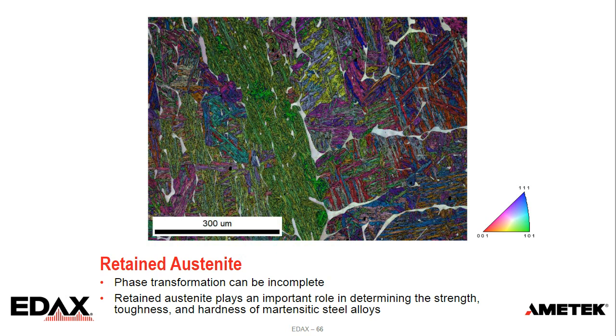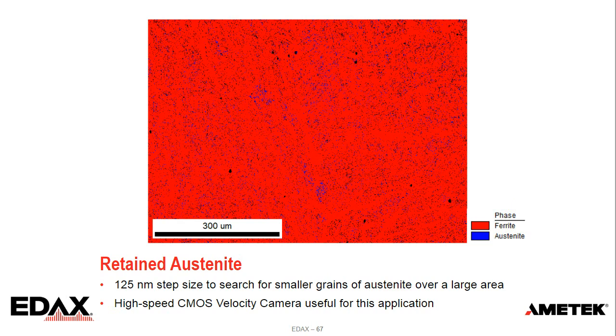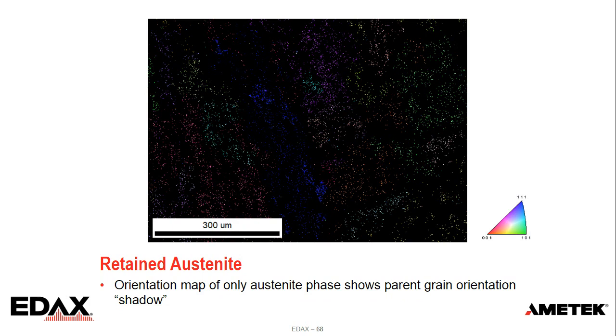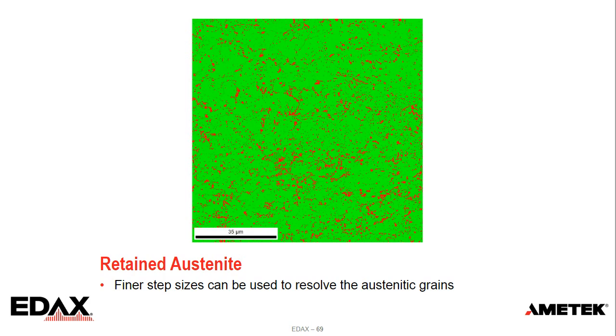So that's what we're showing here, doing 125 nanometer steps, looking at the ferrite and austenite. And the blue are the smaller regions of austenite that are present. And what's kind of cool about this is that as we look at this in terms of an orientation map of just the austenite, you can kind of see the colors, and the black makes it a little hard to see, but you see sort of the shadow or the outline of the parent grain orientation. So this has been used to look at some of the reconstruction as well, to show how it's working and when it's working. So we can measure retained austenite with EBSD. And of course, as we go to finer and finer step sizes, we can resolve more and more of those grains. So it starts to become a sampling statistic, sort of an approach of how to best do that.